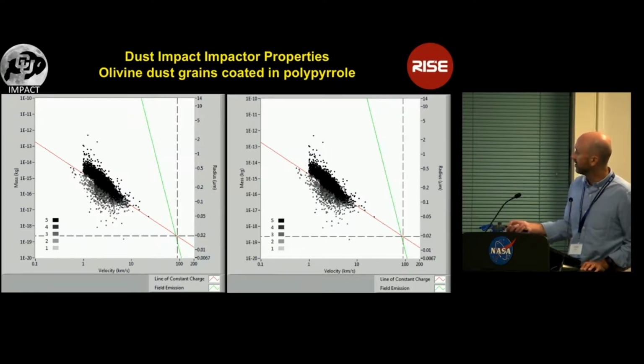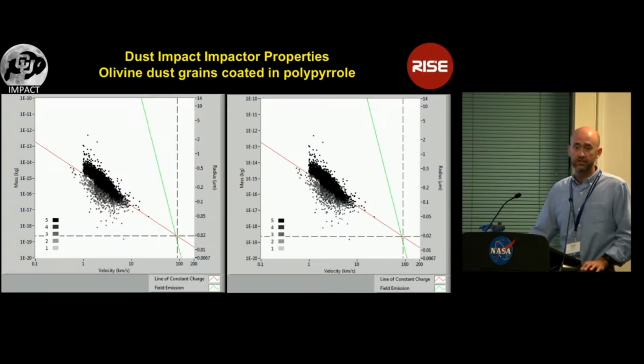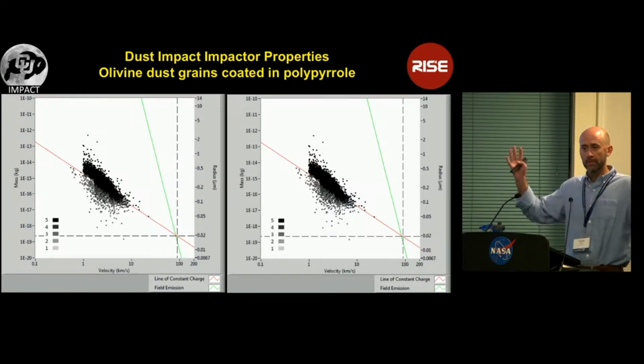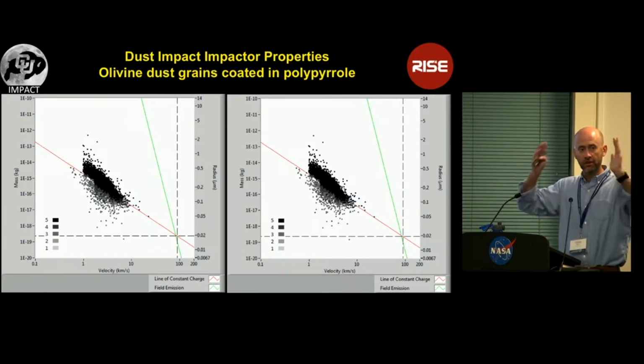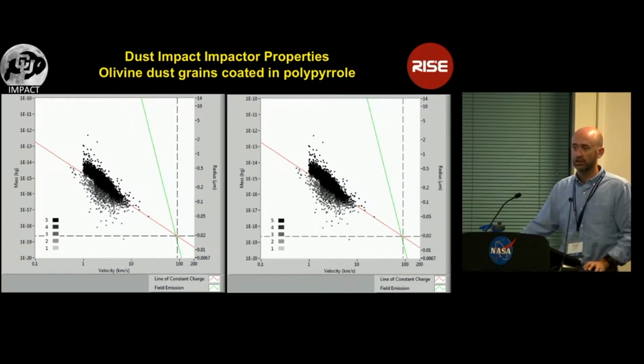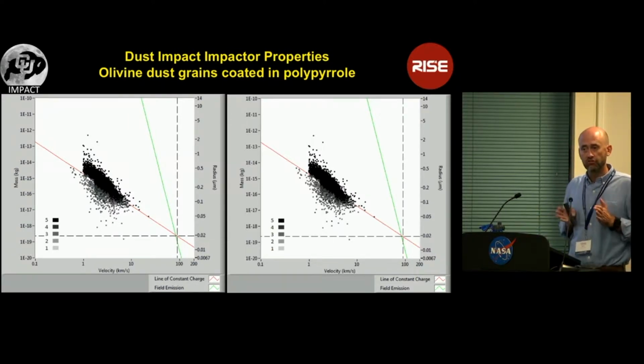And what you're looking at here are the mass and velocity distributions. And so the velocities of our impactors were between about 1 and 10 kilometers per second, with a lot of these being a little bit on the lower end of that scale. For this first set of experiments that we did, we really just wanted to kind of open up the chamber and just throw every single particle that we could at it to see what would happen. In our future experiments, we certainly want to more tightly constrain the velocity ranges to be more appropriate for lunar conditions.